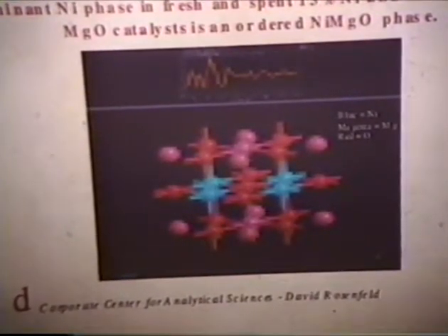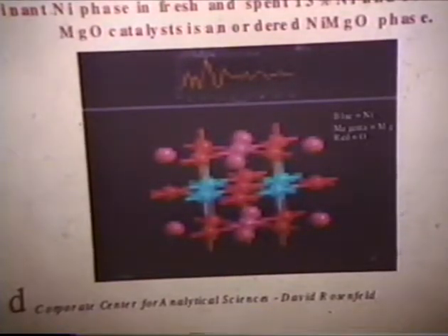So taking the XANES work and doing some modeling with Cerius2, molecular simulations, and this is fuzzy, but anyway, the blue spheres here are the nickel metal, the magenta are the magnesium, and the red is your oxygen. Basically, what it's saying is that to get a pattern that theoretically matches what you obtain experimentally, your nickel is fairly well dispersed as a solid solution as nickel plus 2 prior to use. And so there's some order or pattern there.